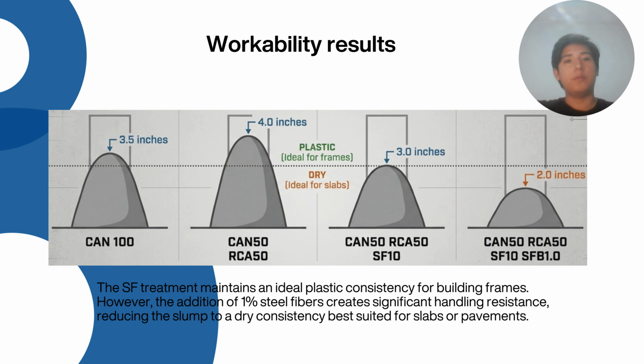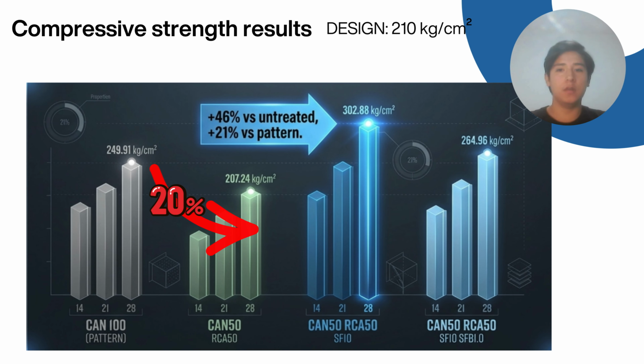Regarding fresh concrete properties, the control mixture, the RCA mixture, and the silica fume treated RCA mixture all achieved plastic consistency, with slump values between 3 and 4 inches. The silica fume treatment could be ideal for building frames. However, the addition of steel fibers reduced the slump to 2 inches, resulting in a dry consistency, best suited for slabs or pavements. We can see here all the results obtained on the compressive strength test.